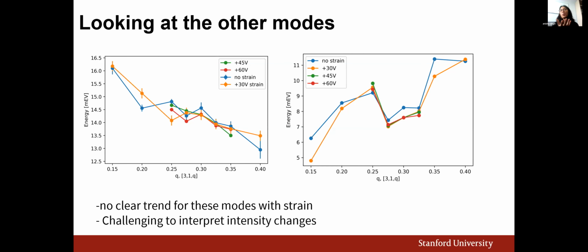So yes, there is no clear change in the dispersion of these phonons with the application of strain. There were some intensity changes in these modes, but again, like I mentioned, these are a bit more challenging to interpret because it is hard to guarantee that we're actually maintaining a consistent sampling of our crystal volume. So since this isn't happening in a very systematic way, it's challenging to put too much meaning into that observation.